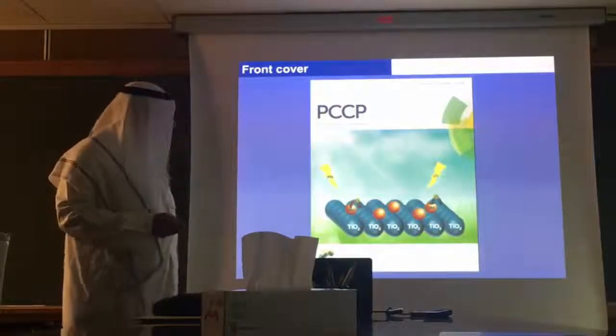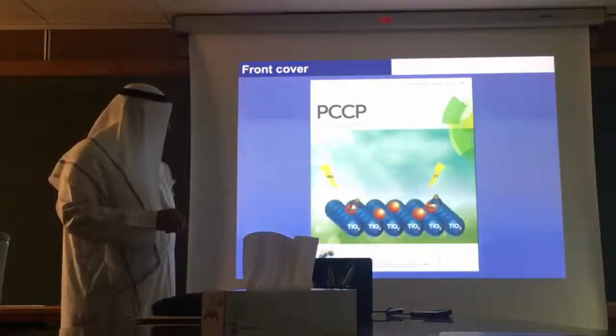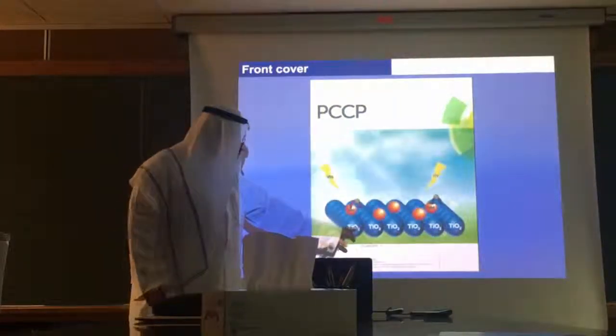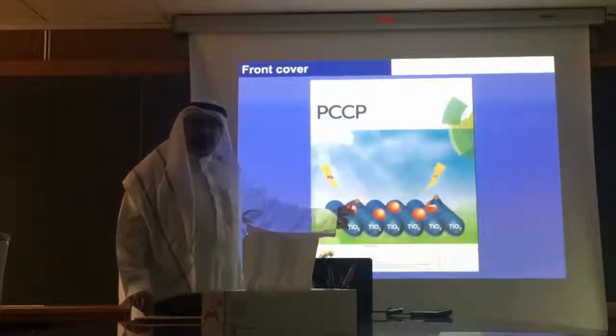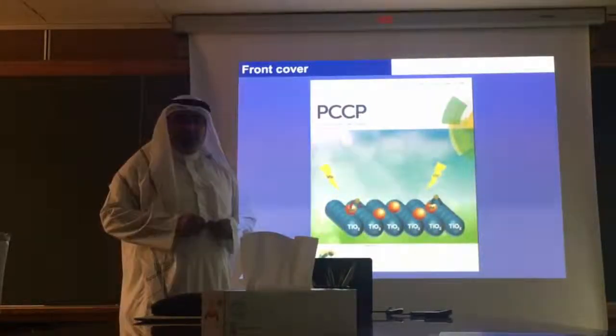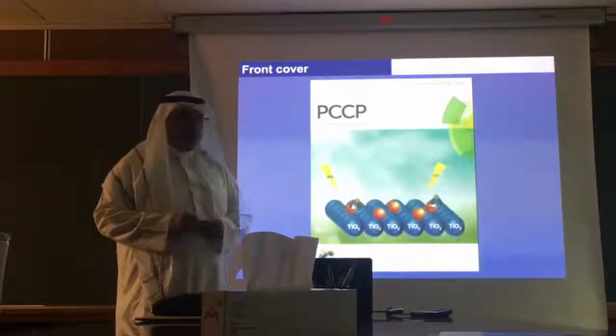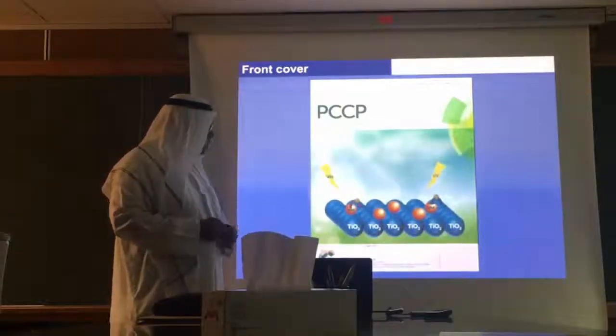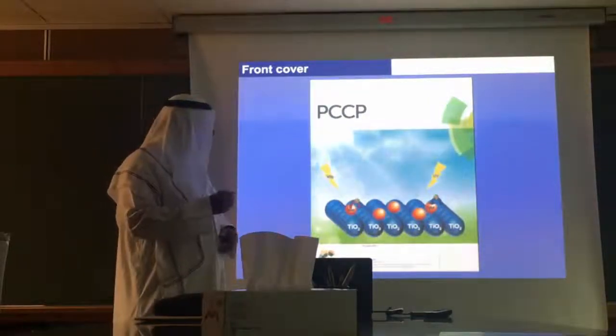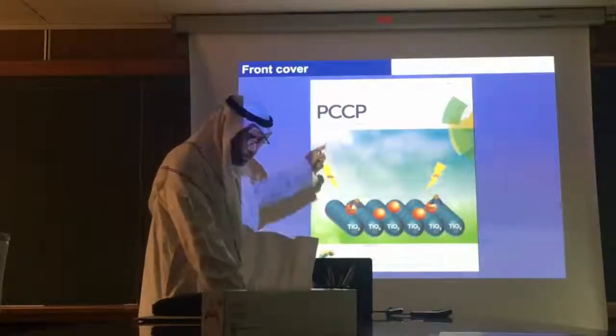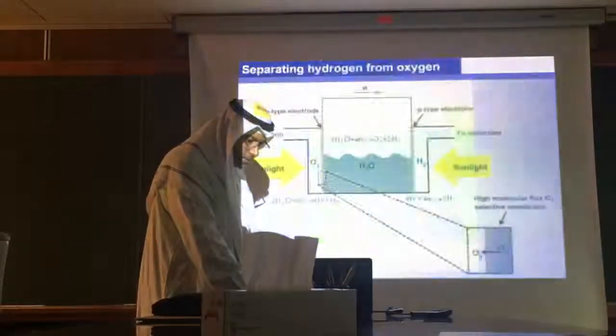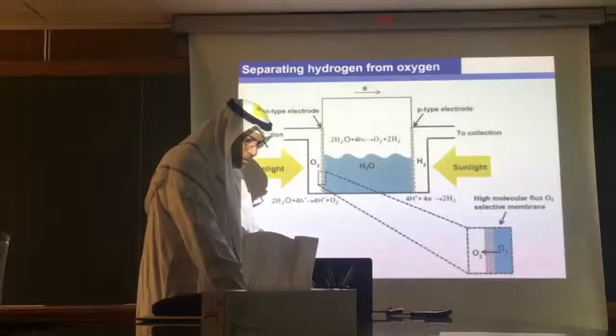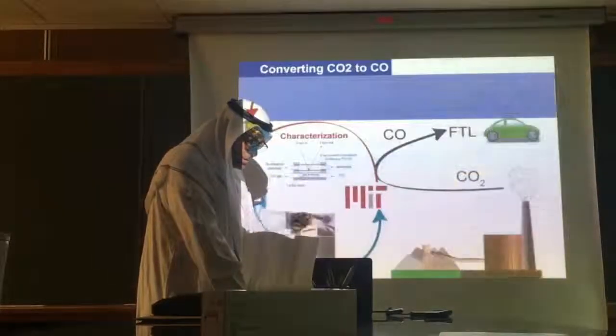This is another work that was selected for a front cover. This is using titanium with gold. You remember I told you, titanium and I put gold nanoparticles. This will delay the recombination between the electron and hole. This was also published in PCCP, which is a very good journal from the Royal Society of Chemistry. This is hydrogen splitting work I did a long time ago.